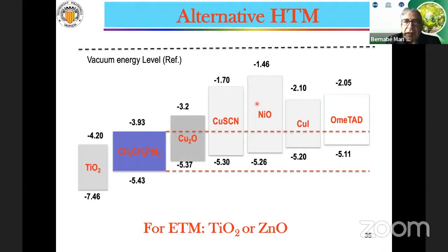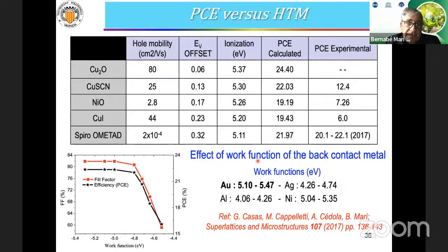Well, we have also worked with alternative HTMs. And in that case, we have made calculations with all these possibilities: copper oxide, copper thiocyanate, etc. These are the results. The result means that the best HTM material, able to produce the highest photoconversion efficiency, is copper oxide. Here we have the different materials and the calculated efficiency, theoretical or experimental. For the spiro, which is the most commonly used, it fits very well. For copper oxide, there are not yet solar cells produced using this HTM.